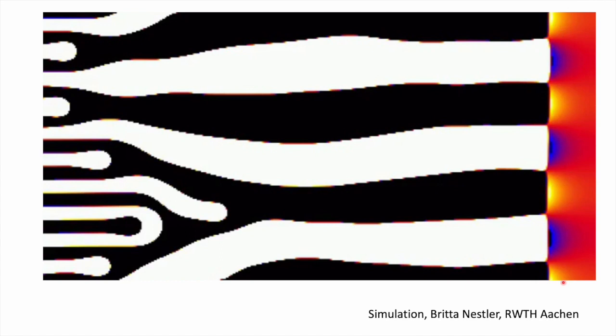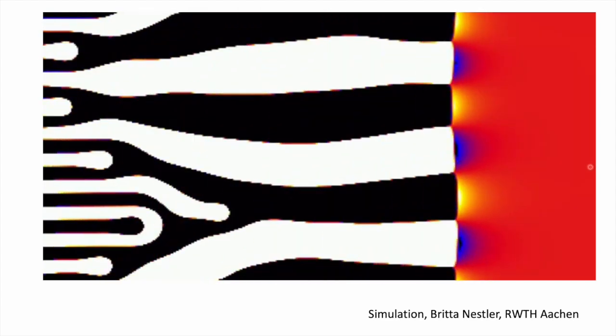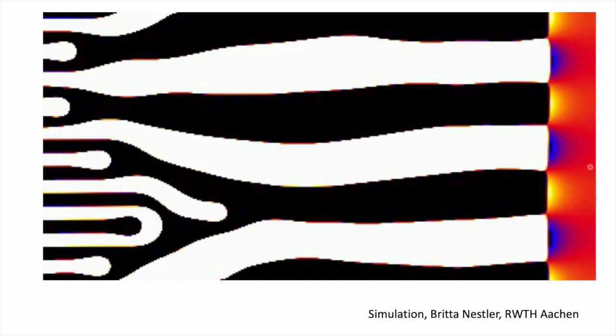And it's a very limited diffusion field because the average composition of the eutectic solid is the same as that of the liquid. That is why this reaction can happen very rapidly, because you are not enriching the liquid with solute, which would then slow down the transformation. The diffusion is basically going from a solute-poor to a solute-rich phase and doesn't extend much at all into the liquid. The far-field liquid remains of the same composition as the average alloy composition. So eutectic transformations can be quite rapid compared with other transformations in hypo-eutectic and hyper-eutectic alloys, where the composition of the liquid actually changes when you precipitate a phase before the eutectic temperature is reached.